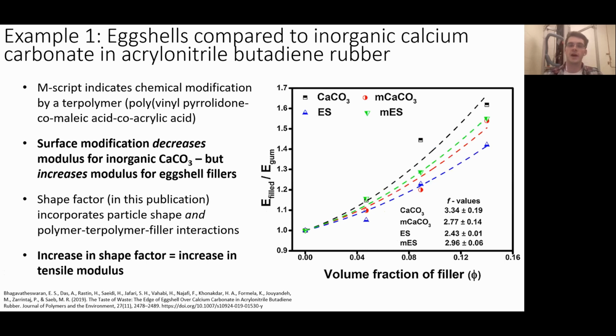So the first paper I want to look at is a paper in which the authors examine the effects of eggshells and inorganically derived calcium carbonate in common rubber. This is an elastomeric material. They also did a chemical surface modification of both materials before using them as a filler with a terpolymer. So this is a surface modification. And then they analyzed the tensile properties of all four composites, right? So they have the modified and unmodified inorganic calcium carbonate particles and the eggshell particles as well.